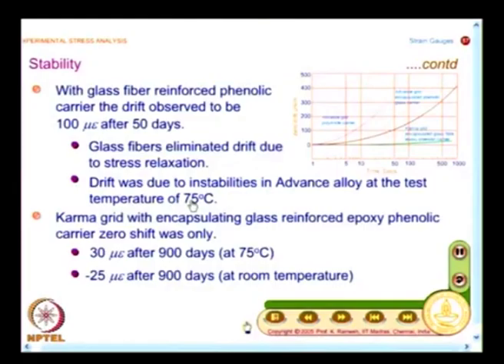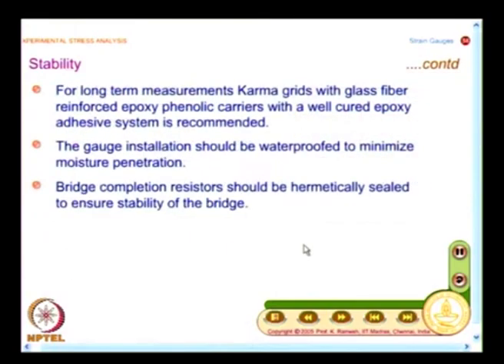So, you need to worry about what temperature you are working at, what backing you are using, and what adhesive. Here the adhesive role is not emphasized that much, and what you find is Karma grid has worked at 75 degrees centigrade quite well. Even at room temperature, instead of positive drift, it has a negative drift of minus 25 microstrain. See, for long term measurements, Karma grids with glass fiber reinforced epoxy phenolic carriers with a well cured epoxy adhesive system is recommended.